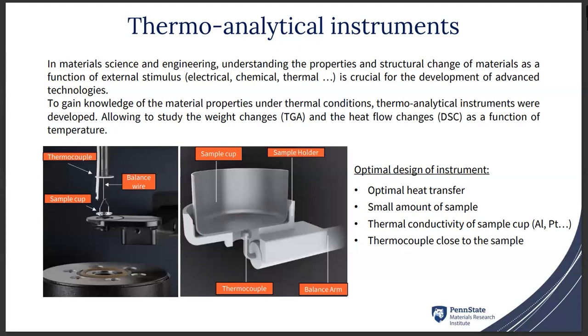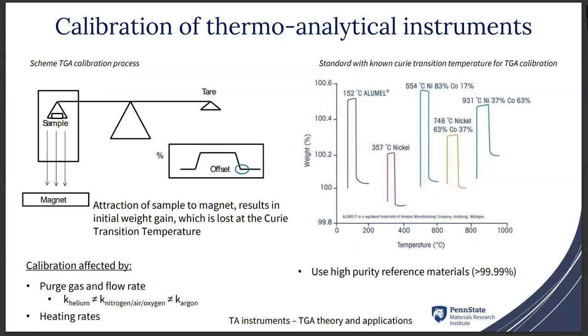Despite this optimal design, the instruments still need to be calibrated. I will present the way the TGA instrument is calibrated. To do the calibration, we need to use a high purity reference material. In the world of TGA, we use different metals or alloys that have very well-defined Curie transition temperatures - the temperature at which the material changes its magnetic property. We load the sample in the TGA, tare the instrument, and put a magnet under the sample, which leads to a gain of mass. Then we do the temperature calibration, and at the Curie temperature the weight goes back to its initial value, which gives you the actual temperature inside the instrument. There is no change of sample mass, it's just the change of the property.